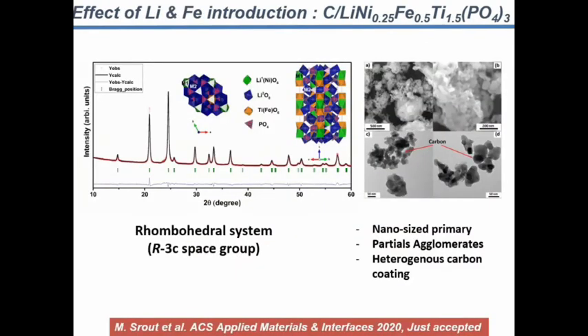cycling. The second example that was just accepted in the ACS Applied Materials & Interfaces journal consists of introducing lithium and iron in this nickel titanium phosphate. So we substitute some nickel ions by lithium and iron, and we obtain this formula. And once again, we use a very easy synthesis method, and we got by XRD a pure phase as revealed by the Rietveld refinement here, and the structure is a NASICON type structure with the space group R-3c.